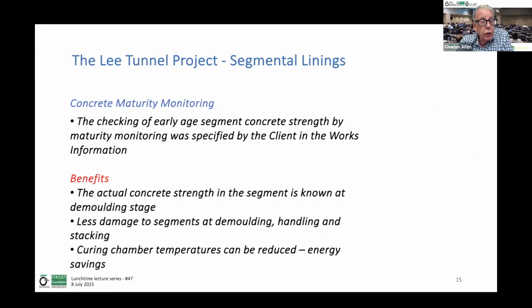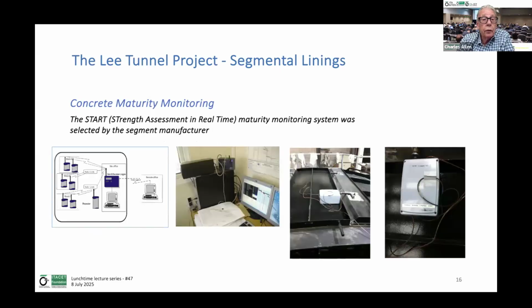You're not trying to crack a cube and compare it to your in situ strength, because the cube strength will always be lower than the strength of the concrete in the mold. You get less damage to segments at demolding, handling and stacking, and curing chamber temperatures can be reduced, which gives you energy savings in the production of the segments.